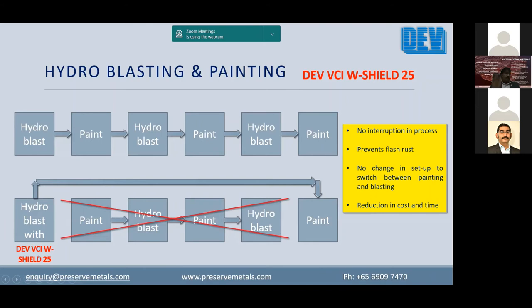If it's an internal surface, we use the hydroblast water with the WS-25. If it's an external surface, wherein the water is not collected and recycled, once you do the hydroblast, immediately spray the surface with WS25 30% solution. This will ensure that you don't have to keep your paint team on standby. You can do the hydroblasting of the entire surface, then demobilize and start with your painting.